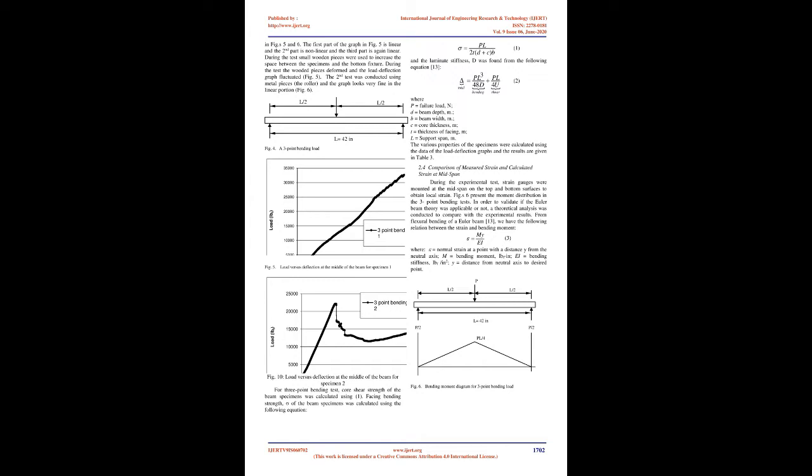The testing beam consists of rectangular end-grain balsa wood core wrapped circumferentially with 2 layers, +/-45° orientation, of E-glass fabric, then longitudinally on the top and bottom surfaces with 2 layers of the most dense hardwood, then transverse to that 1 layer of medium-density hardwood. Lastly, the outer surfaces were wrapped with random glass mat, for an impact and water-resistant outer layer of approximately 0.1 inch thickness. The entire assembly was vacuum infused with vinyl ester resin containing single-wall carbon nanotubes.